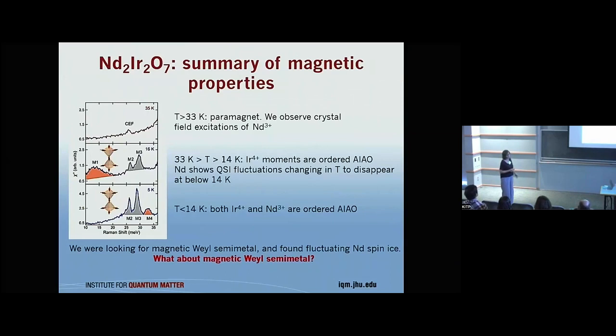We do observe the crystal field of neodymium at temperatures when no magnetic order is there. Then below 33K, we observe the magnon response of the iridium sublattice, which is ordered all-in, all-out. Just below this ordering of iridium, we start to observe the spinon response of two-in, two-out fluctuations of the neodymium sublattice, which then eventually decreases as we get all-in, all-out correlations in the neodymium sublattice and disappears below the transition, and instead we observe a two-magnon excitation of neodymium.